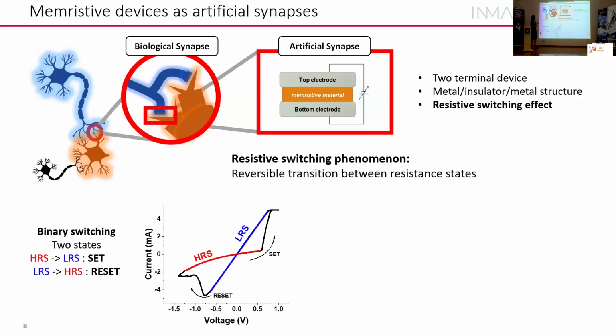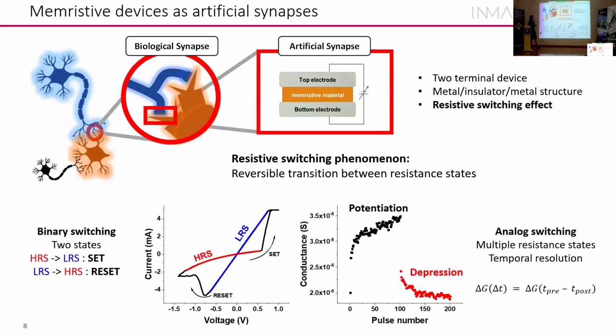Okay. And how do we get this resistive switching effect? So we apply a voltage. If we start with an insulating material, we have a high resistance at the beginning. We would be on this red line here, okay? And then one of the electrodes is grounded, and to the other one we apply a voltage. And when the voltage is high enough, we change the material to the low resistance state. And then we stay in this low resistance state until a high enough voltage is applied in the opposite direction. So by applying a positive or negative voltage, we can change the resistance state from high to low resistance. Okay. What else can we do?